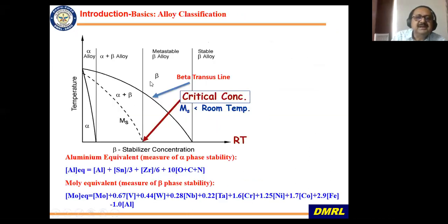Here, I am showing the pseudo binary phase diagram where you have temperature on the y-axis and beta stabilizer concentration on the x-axis. Now, there are two empirical formulas. The first is for measure of alpha phase stability, and it is known as aluminium equivalent. You put in the weight percentages of the elements that you have in the alloy, plug into this, and you get a number. So that is known as the aluminium equivalent. So you have aluminium, tin, zirconium, and oxygen, carbon, and nitrogen.